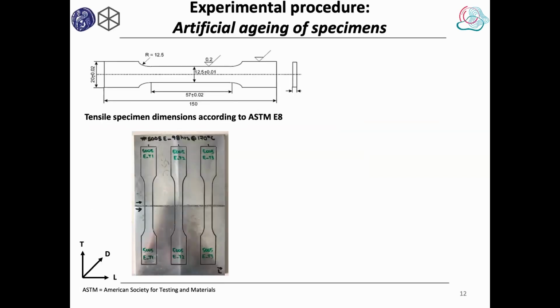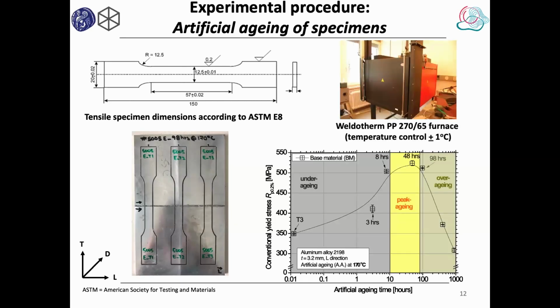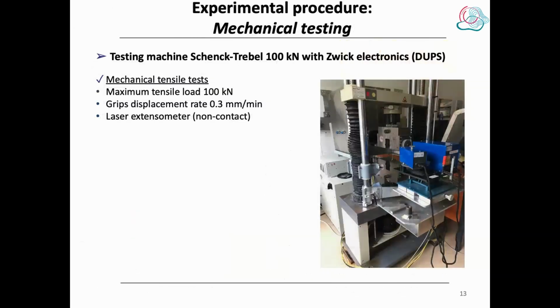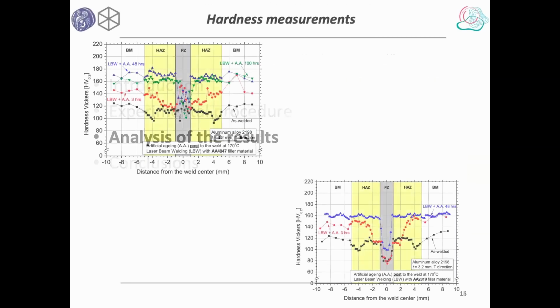Okay, here is the overview. For characterization, we used tensile specimens extracted from the welded sheet in the middle, and we performed heat treatment and tensile testing. For heat treatment, we used the typical furnace, and heat treatment was performed for different times, between 3 hours and 98 hours. Okay, and for mechanical testing, we performed tensile testing using an electromechanic testing machine, for example, this one in our laboratory from Zwick. And here are the results.